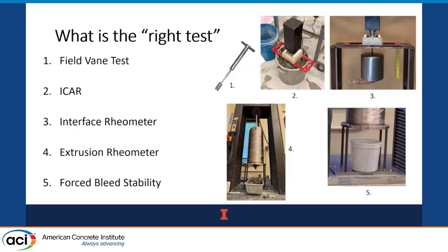Then Ben got really involved in building, and so we got an extrusion rheometer, where now we're measuring the force that it takes to extrude the material through an orifice. And last but not least, we also really started to look into the susceptibility these mixes had to bleeding. With all of that in mind, we also threw in this field vane test, which Nathan found for us because, hey, this is something that they could just run while they were printing and keep an eye on the change in yield stress within their mixes. Okay, so Ben really threw the kitchen sink at this to try to characterize everything.